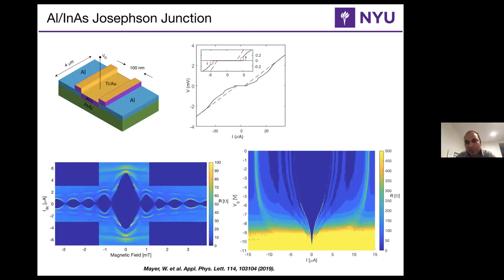So if you have a good Josephson junction, everything is healthy, you see a good Fraunhofer pattern, and obviously a supercurrent on the top main panel. There's hysteresis in our junctions usually because of heating in these junctions. We can usually measure at a higher temperature to make it go away, or you can shunt it, but shunting is a little bit tricky because some of the junctions, depending on the geometry, could have a high RN, and that can cause trouble.